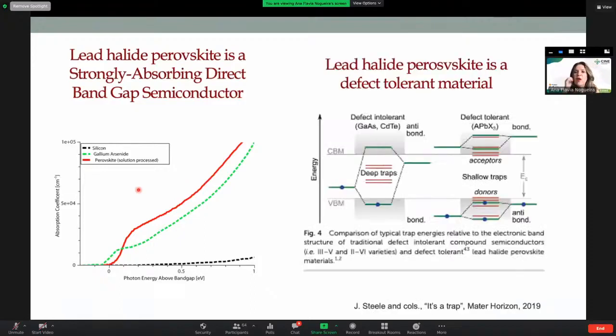In terms of the defects, this is what I mean by shallow. What are shallow defects? For gallium arsenide and cadmium telluride, which is the second generation of photovoltaics, the traps are located in the middle of the band gap. Because of the nature of the composition of these perovskites, the traps are very close either to the conduction band or to the valence band. It means it's quite easy for the electrons or holes trapped in these levels to leave these traps and move through the crystalline structure. That's the reason the defects are shallow.